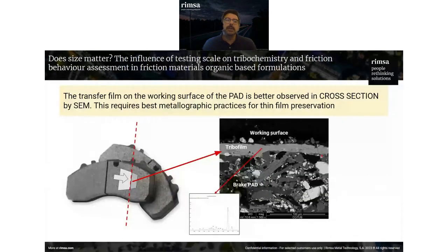So this transfer film, if we take the cross-section of a brake pad and we see the working surface, we are going usually to find this kind of tribofilm. This is something that is related to the tribochemistry, so the mechanically induced reactions that take place on the surface of the rotor, on the surface of the brake pad, and all these debris, and how these debris are incorporated or are kept or are released from the surface of both the parts. So it's very important for the tool we use to assess the coefficient of friction and to do the research that it is able to replicate this tribochemistry in the same conditions or in close conditions to the ones we are going to obtain in a bigger machine or testing machine like a dynamometer or in the car.